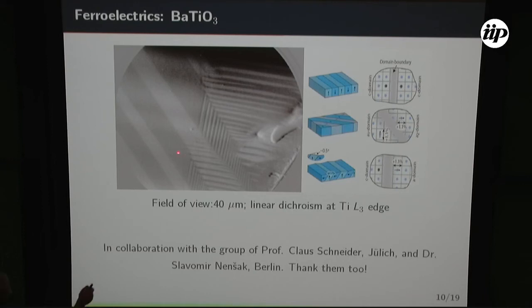Indeed, the ferroelectric distortions on the BTO, for example, induce this anisotropy that I mentioned at the beginning that can be probed by linear dichroism. So using the contrast based on linear dichroism, you can image the domains, the ferroelectric domains. In this case, it is a monocrystal of barium titanate, okay?